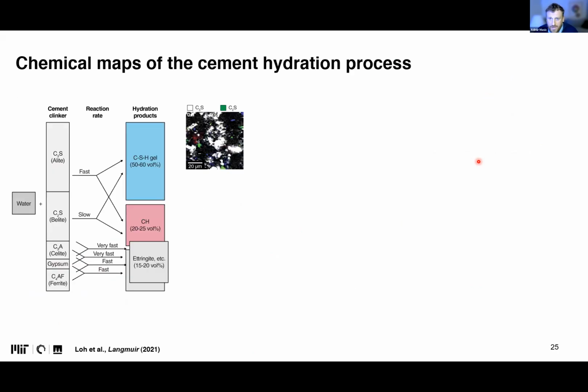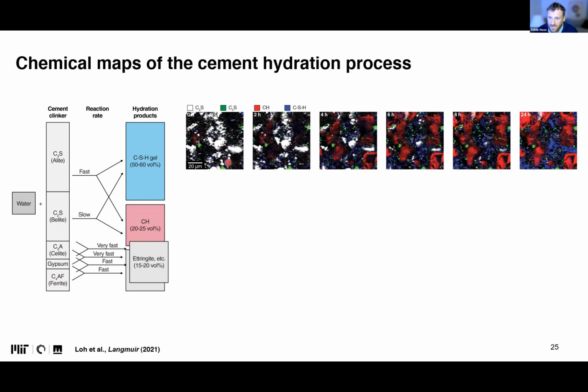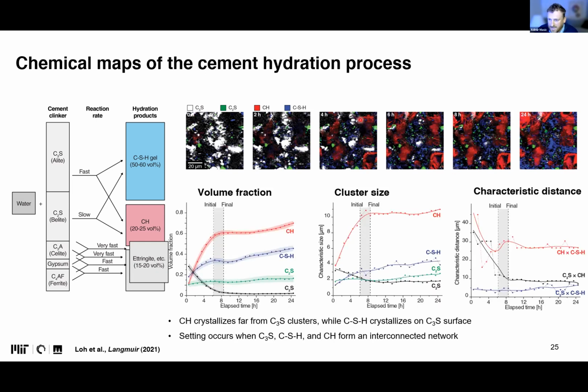The cool thing, as I said, is that we can get spatial resolution, not only temporal and spectral, but also spatial resolution. So you see these are snapshots of that video, and you can nicely see that, for example, in this corner there's a lot of calcium hydroxide forming, and then you can analyze this through correlation functions, and you can get the volume fraction, cluster size in microns, and characteristic distance just by analyzing these images.